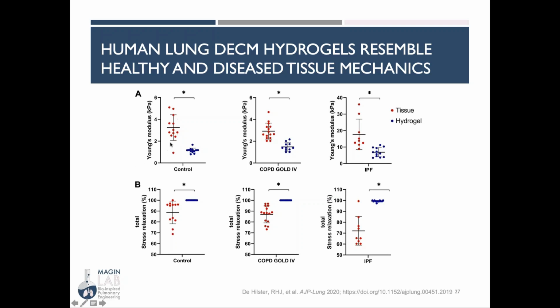You can see control healthy lungs range from 1 to 5 kilopascals in Young's modulus, and when you recreate that with a hydrogel, you get something similar, a little bit lower modulus. In COPD, you have a slight drop in modulus from your healthy control samples. And in IPF, please notice that this scale is much different. This is 40 kilopascals instead of 6. You see a significant increase in the modulus of the tissue that has started to be replicated in the modulus of the hydrogel. So it's really fascinating that these hydrogel materials also retain some of the mechanical properties that have been changed in the microenvironment of lung disease when the lungs are no longer healthy.